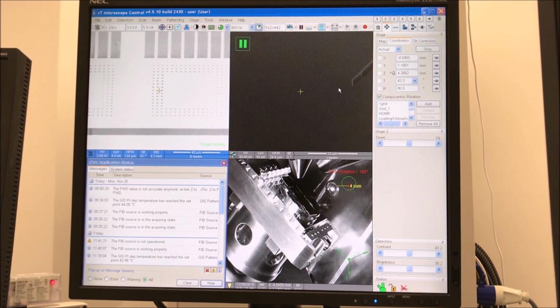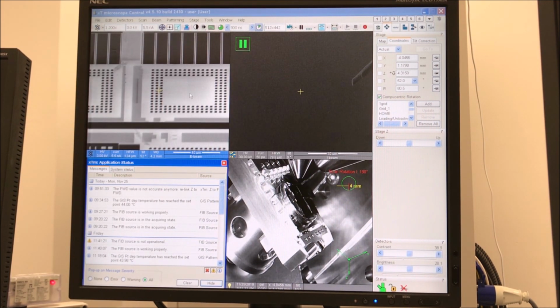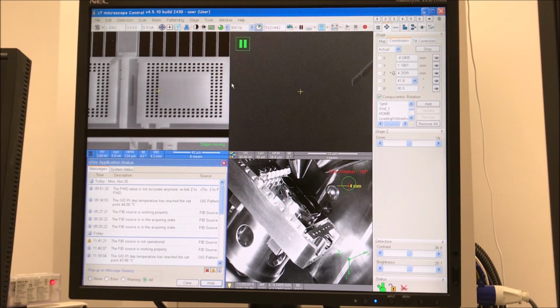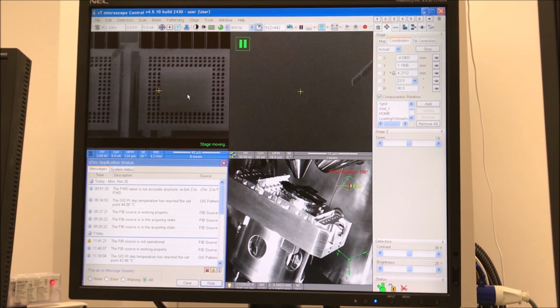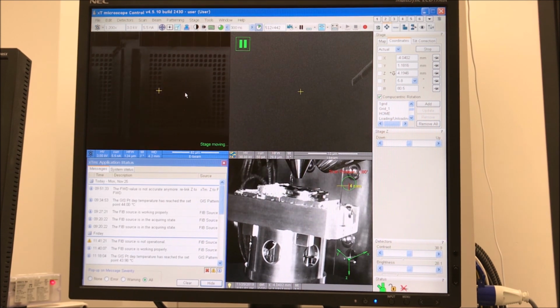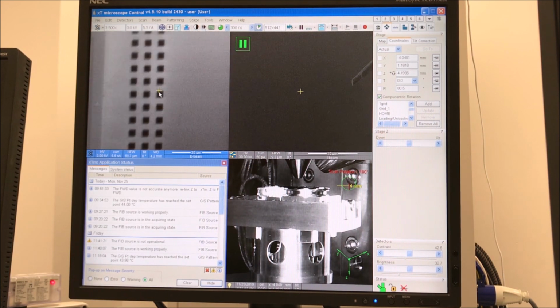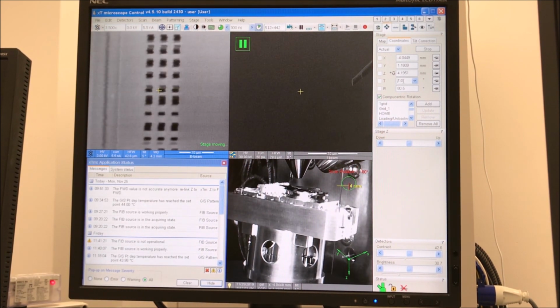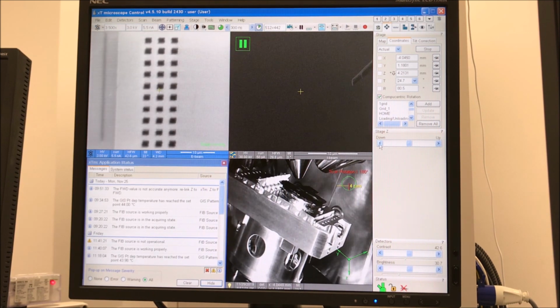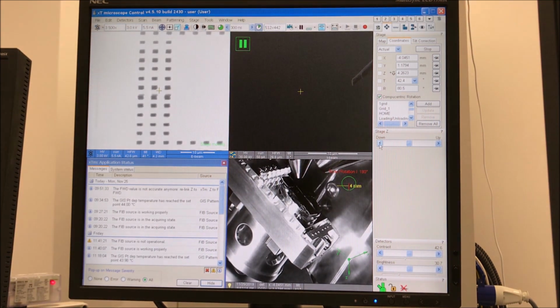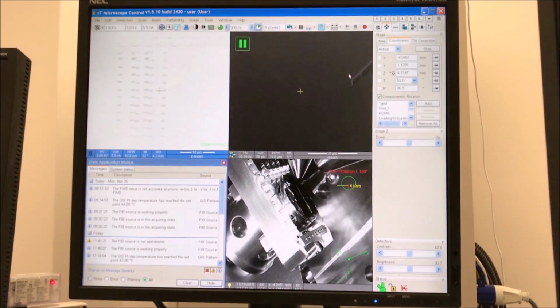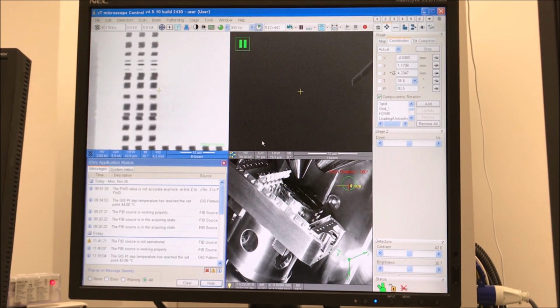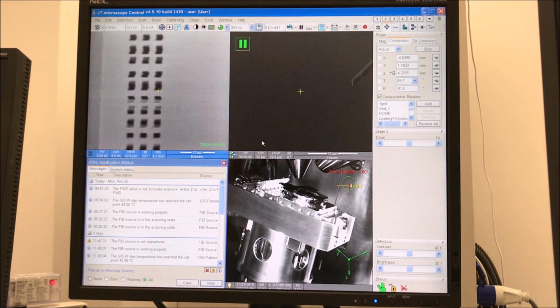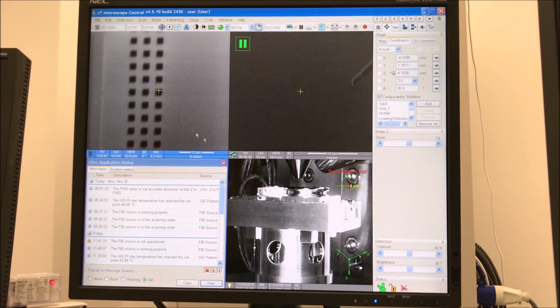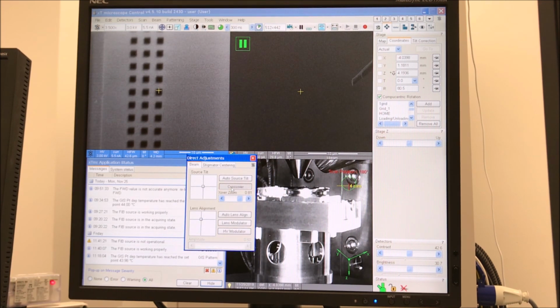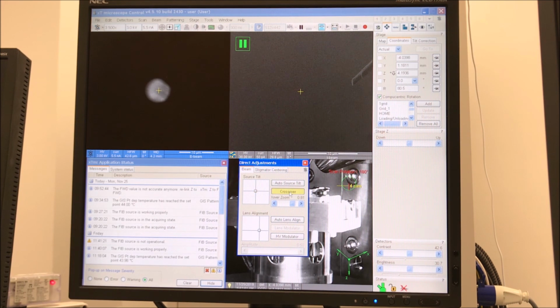And again, I'm going to do this iteratively. You can see that the contrast in the image changes as the stage is tilted. So feel free to perform auto contrast and brightness as needed. The hotkey for that on the keyboard is usually F9. You can see it's getting really bright, so you could have done auto contrast, although I didn't do it here because I knew I was going to tilt back to 0 anyway to do the E-beam deposition. And so now I'm back to 0, and I'm going to do the alignment.